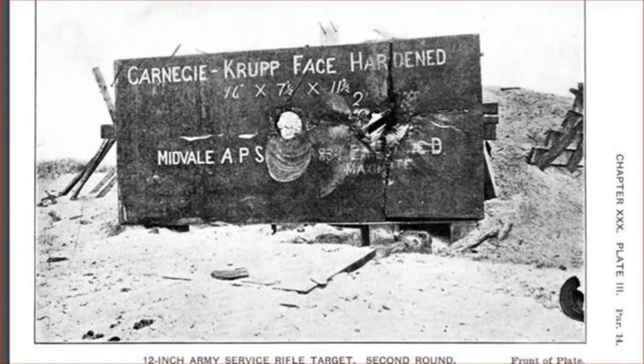Now, this did result in absolutely phenomenal performance when it was used at cruiser-grade thicknesses against cruiser-grade guns, with the lighter-weight 6-inch and 8-inch projectiles smearing themselves all over it like flies over a windscreen. But past about 12-inch caliber shells, the scaling effect that had been noticed with the more extreme armour that we talked about from the Midvale 1910s era testing began to reassert itself, and this left Class A armour as of pretty decent material quality, but somewhat less actual resistive value compared to similar thicknesses of other nations' battleship plate going